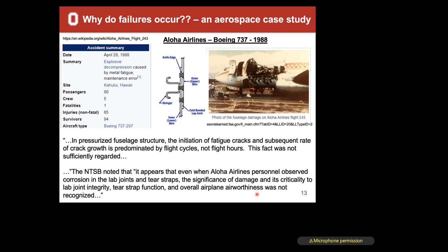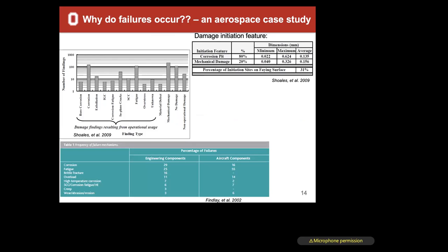So this failure was actually quite catastrophic, and it got a lot of attention towards this kind of aging aircraft and the effect of corrosion on material failure. In fact, doing my PhD work in the early 2000s, the after effects of this crash actually led to the funding that I had for my PhD as well. And it's a lot of the reason why the military spends a lot of money on corrosion issues because of this specific failure and the light that it brought to the impact of corrosion on material failure and metal failure in aircraft. You can see some of that actually shown through some data here.